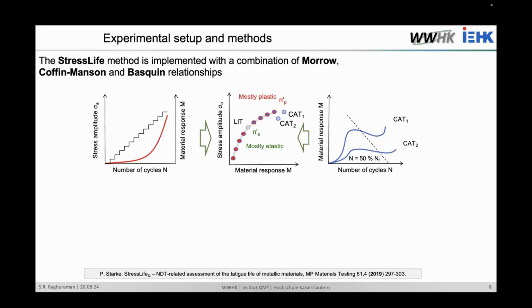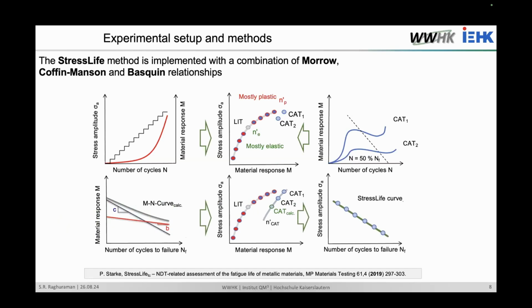Here we'll be conducting one load increase test and then two constant amplitude tests. And we'll be putting the data that we have obtained together in a Morrow equivalent plot. And then the next step will be visualization of the material response against the number of cycles to failure. The next step will be taking the data that we have so far and using it to calculate further coefficients and exponents that we need for calculation of the stress life curve.